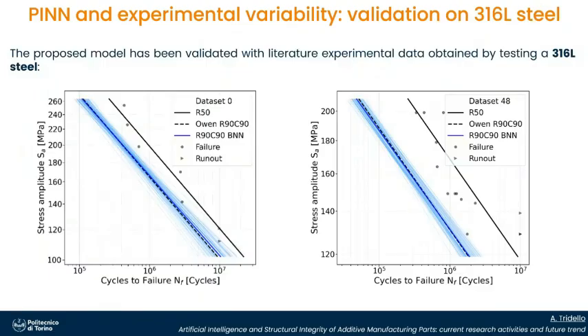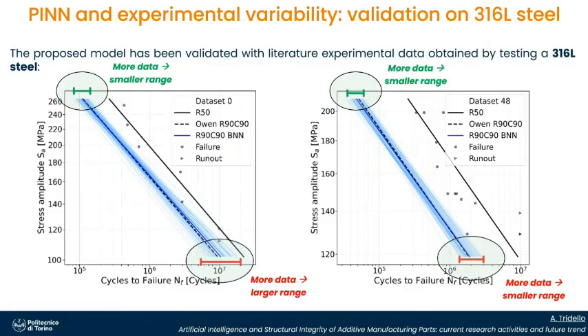Here you can see the results. This bundle of curves includes experimental data. We have also other validation, but I have focused on this one. And you can see that where we have more data, we have a smaller range of the prediction. Where we have less data or run-out, we have a larger range of the prediction. And this is quite expected, and this is good from our point of view, since where we have less data, we are less sure to estimate the real curve.